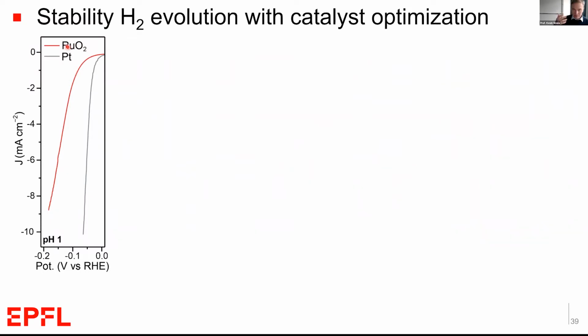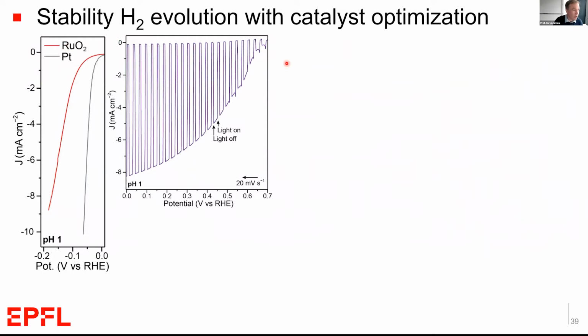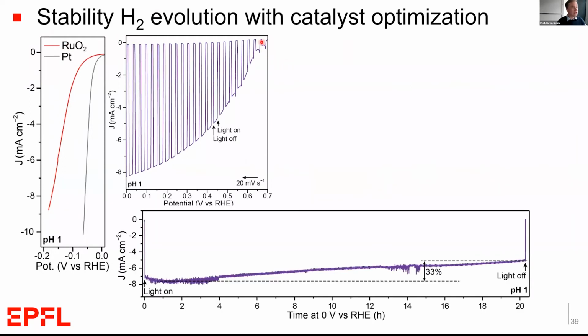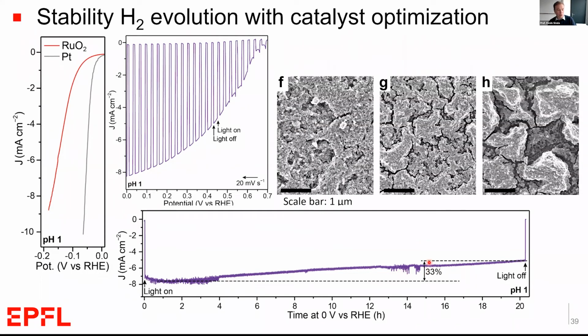And I'm aware that ruthenium is not a very earth-abundant material, but it works quite well to demonstrate that if we choose the right catalyst, we can get high performance, up to 8 milliamps per centimeter squared, and pretty good stability, at least in this case, only losing about 33% of the performance over 1 day of continuous operation.